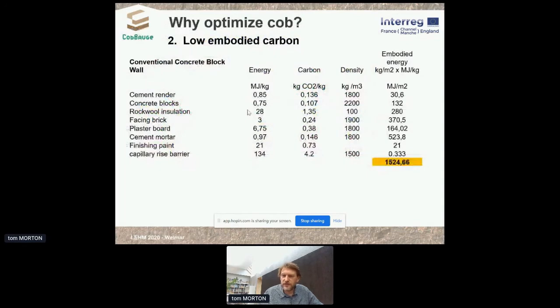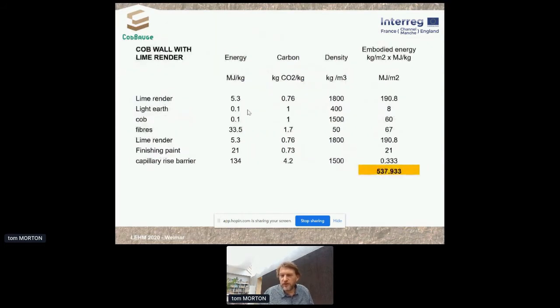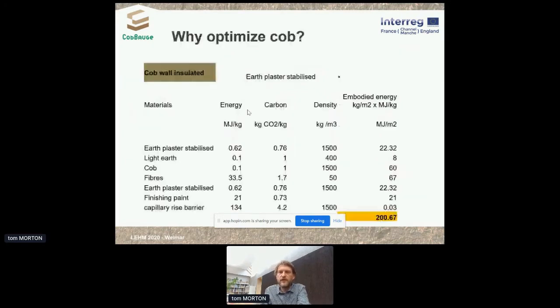And the second reason is to reduce carbon emissions. A concrete block wall is typically about 1,500 megajoules per meter squared. And a cob wall with lime renders is about 540 megajoules per meter squared. And if we use earth renders rather than limes, you can get that down to about 200 megajoules per meter squared. So vastly lower carbon emissions than conventional construction techniques.